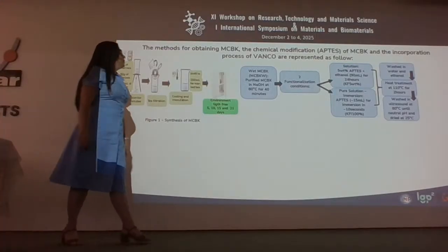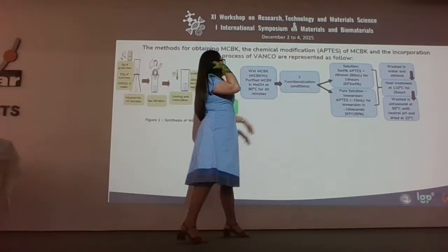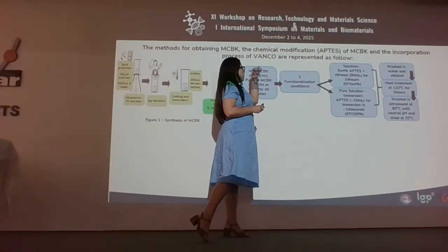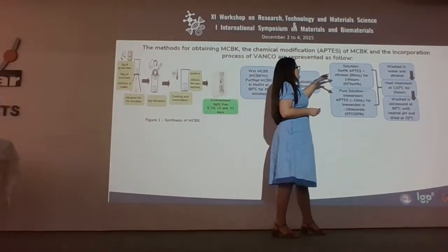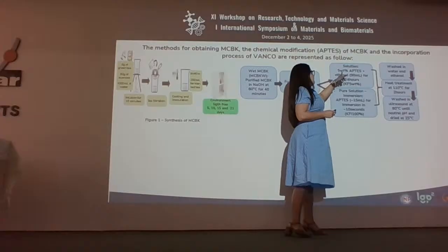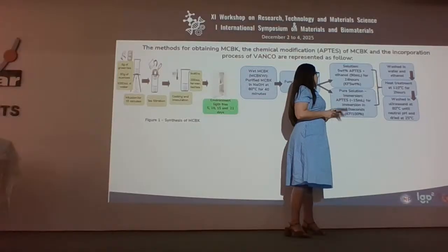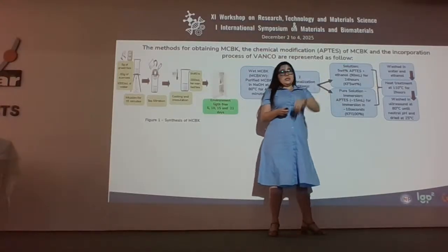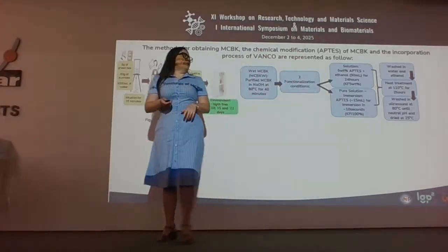And the second part is chemical functionalization, where I use two different conditions with APTES. In the first, I use an APTES solution at 5wt% for 24 hours. And in the second condition, I use pure solution for immersion for a few seconds.